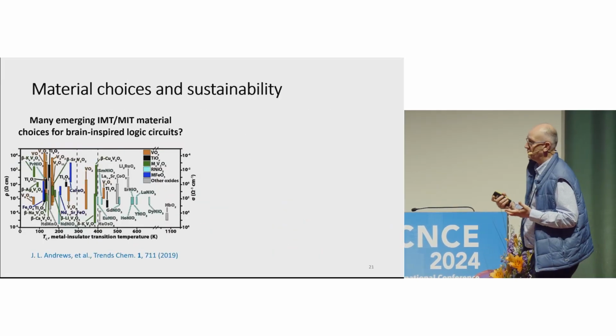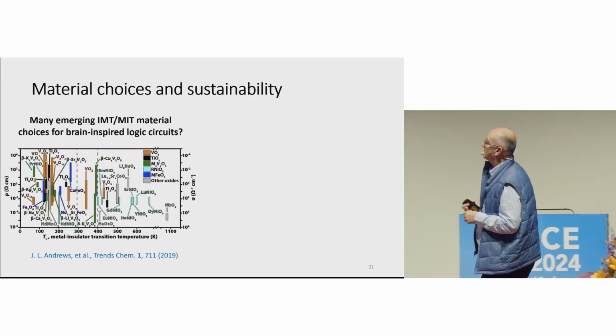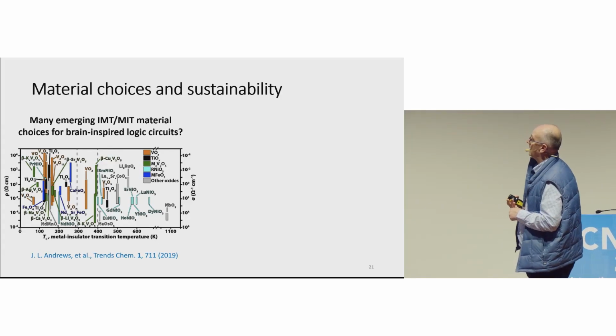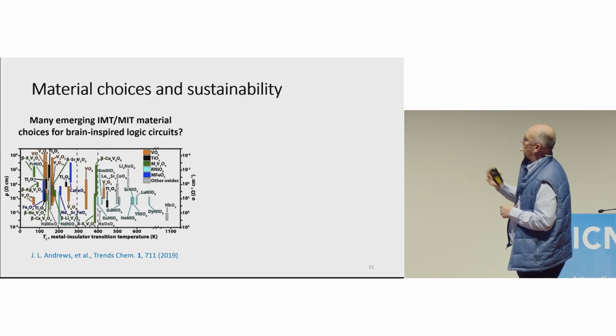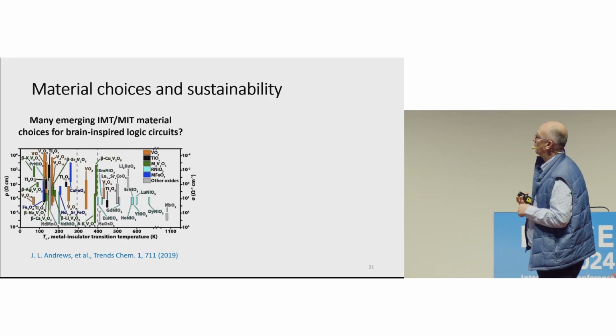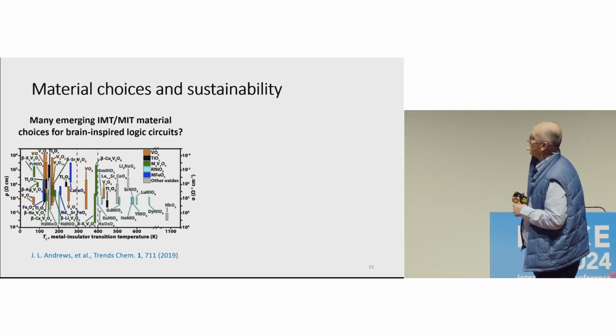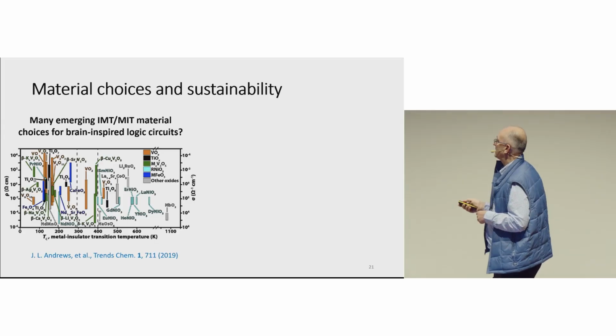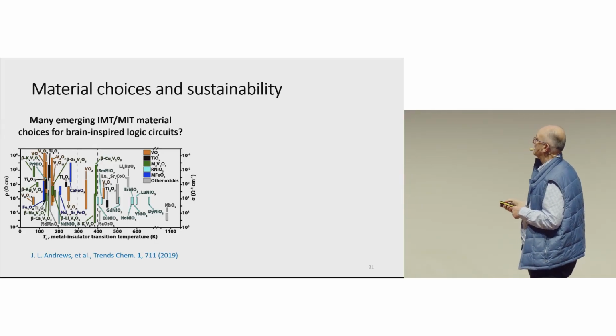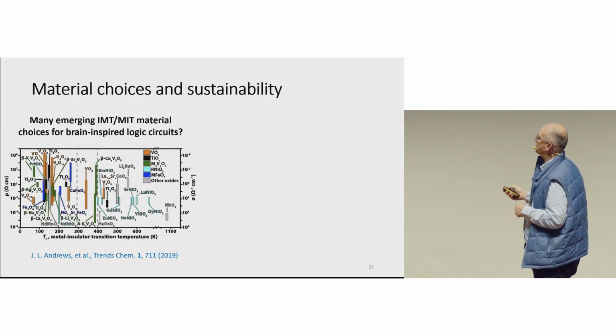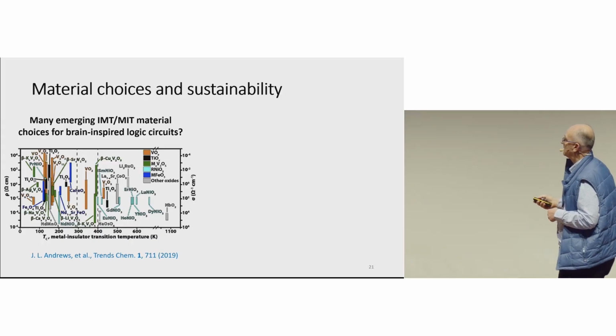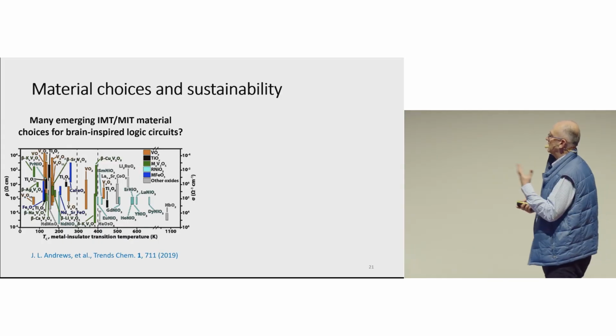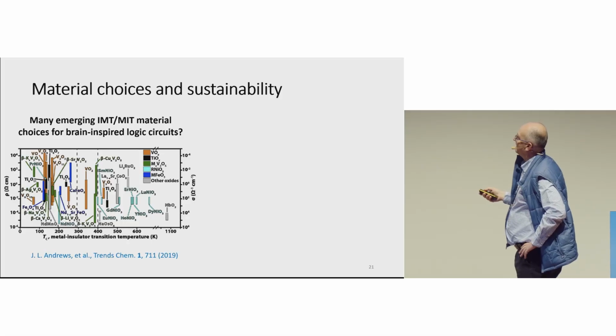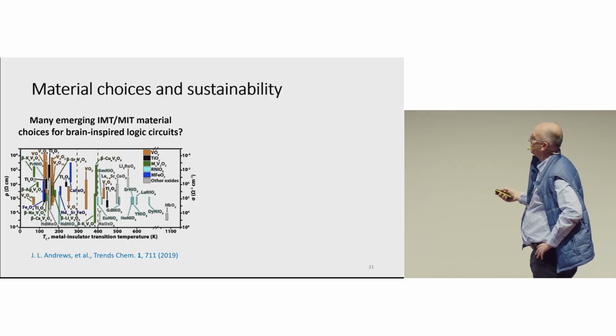Now, there are many materials you can use for that. Among these, you see here a multitude of metal oxides and oxides of different alloys of different metals. The interesting parameter you have to look at is the transition temperature, the horizontal axis. This should be higher than room temperature, 300 Kelvin. And then you need a high contrast, so this vertical dimension of the bar should be as large as possible. For a good switch, you need 2-3 orders of magnitude. And you see, vanadium oxide stands here as a very, very interesting candidate.